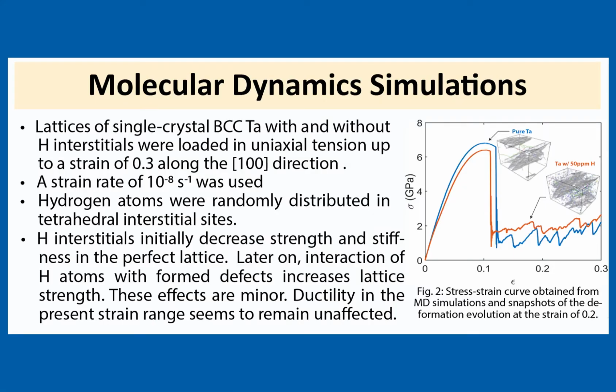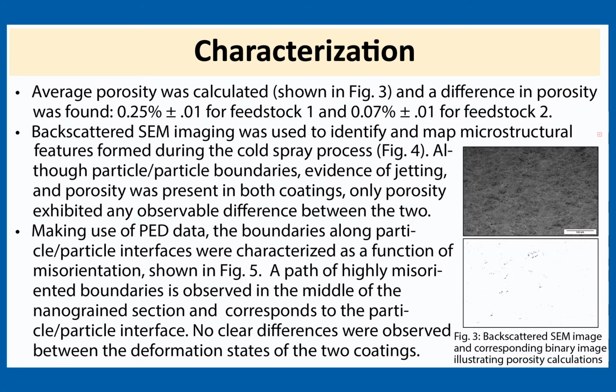Molecular dynamics simulations revealed that hydrogen interstitials initially decrease strength and stiffness in the perfect lattice. Later on, interaction of hydrogen atoms with defects increases lattice strength. Ductility remains unaffected. Different techniques were used to characterize the microstructure of the coatings.